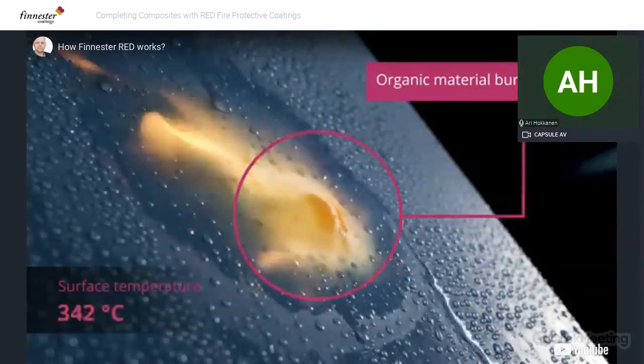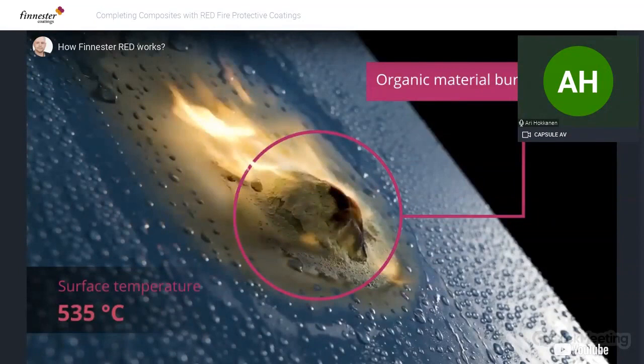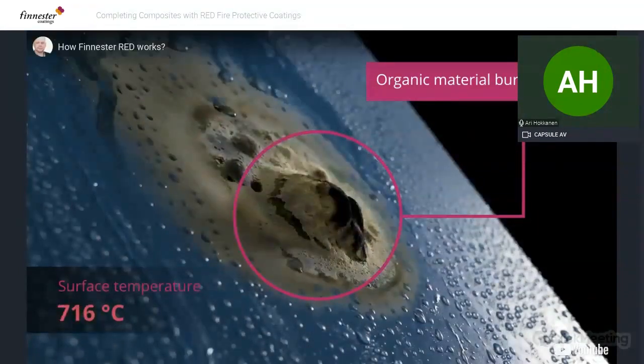Okay, maybe it's not the best image for the pause, but what happens next? The organic material burns away. So there's some organic material, hence the name hybrid, inorganic, organic. So the organic material burns away, and that's completely okay. At the same time, let's watch it further like this. About this stage, about 700 degrees, all the organic materials are gone, and inorganics are left, and the ceramification process starts to begin, or is already in process. At the same time, the heat will transfer to the other side of the ceramified coating to the pure Red layer, and that starts to expand. So that's our intumescent bottom layer that starts to expand and creates this kind of ceramic bubble.